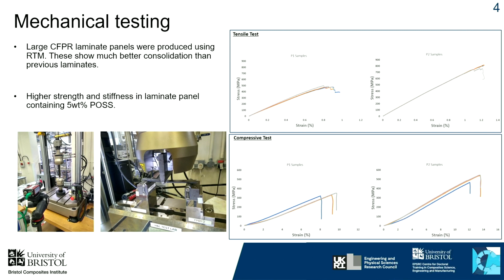So the oxygen resistance was the primary impetus for including POSS, but it also has quite a beneficial effect on strength, stiffness and mechanical properties. After producing some large composite laminate panels, about 0.5 metre in size, we've done a range of mechanical testing: tensile, compressive, flexural and shear. And you can see P1 is the 0% POSS, P2 has 5% POSS. You can see there's quite a big increase in the strength and stiffness of the composites.